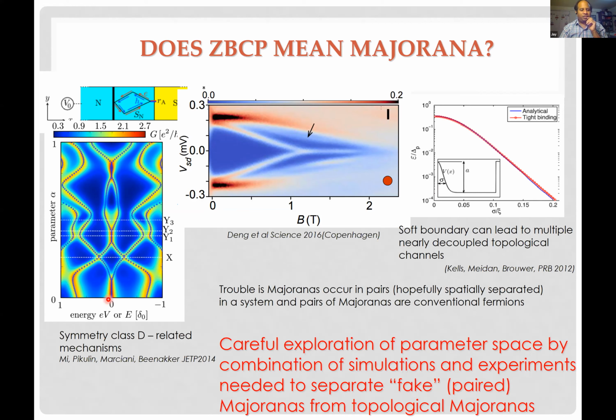I won't dwell on it in the interest of time, but just to summarize it, if you have a disordered superconductor in a magnetic field, there's a random chance of hitting zero bias peaks as you vary the magnetic field, or any parameter, with some frequency. Then it becomes a quantitative question about whether the range of the zero bias peak is large enough. And this is an experiment where the data looks very much like this kind of zero bias peak.